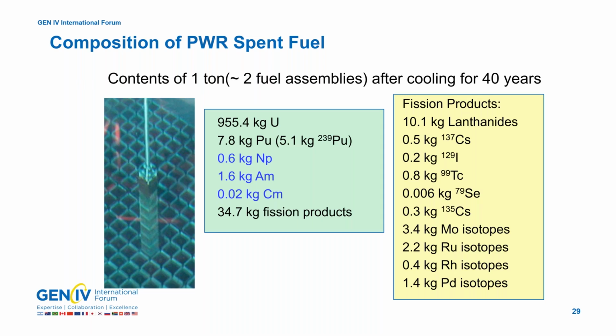This shows the typical composition of the spent fuels, about 1 ton, almost 2 fuel assemblies, after cooling 40 years. There is mainly the uranium left, and there are some plutoniums in this amount, and minor actinides, and fission products. In these fission products, there are some lanthanides. Rare earths are included in these lanthanide elements. And from these spent fuels, pyroprocessing extracts TRU elements through 2 steps. First step is to convert this uranium oxide to metal by the reduction process. And the second stage is from the metal, TRU is extracted through the electrochemical process.